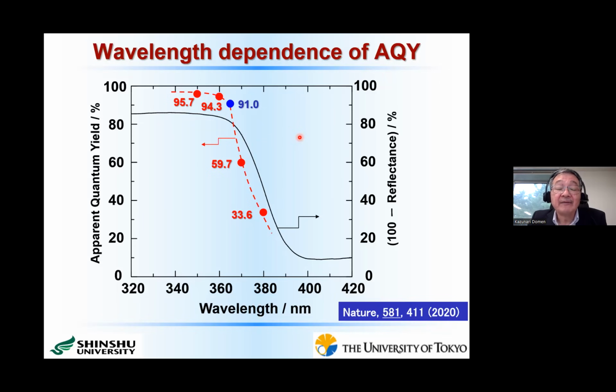So if we evaluate the quantum efficiency based on the total photon number which was really absorbed by our photocatalyst, and we say that it's internal quantum efficiency, at least in this region, we believe that internal quantum yield is almost 100%. So I would like to say that it is now possible to split pure water into hydrogen and oxygen with a quantum efficiency of almost unity using a particulate photocatalyst.